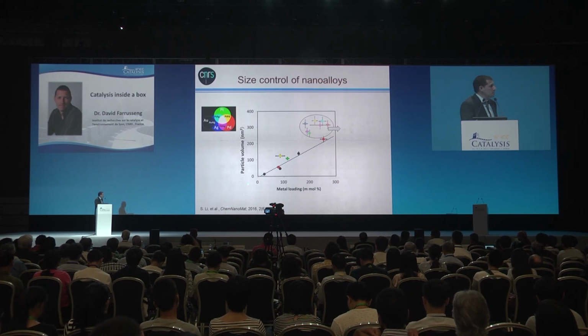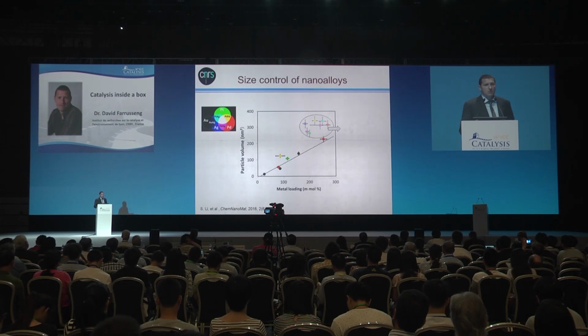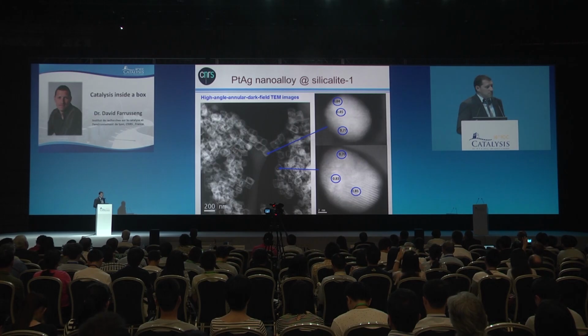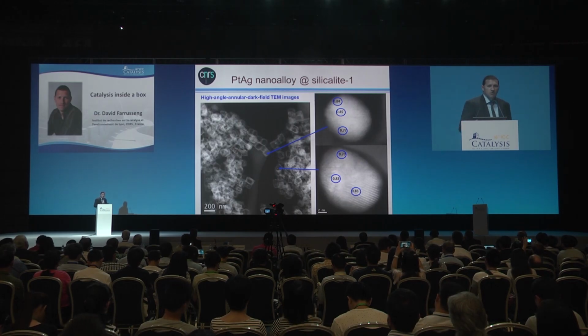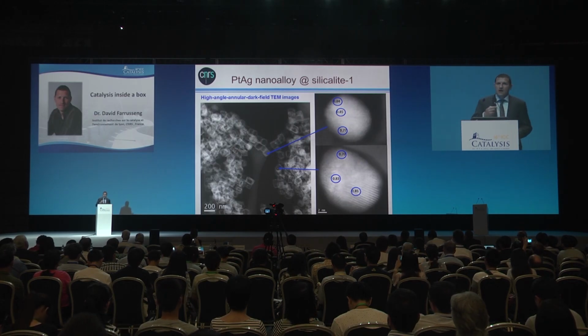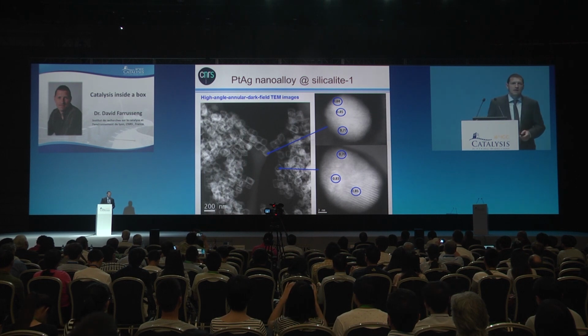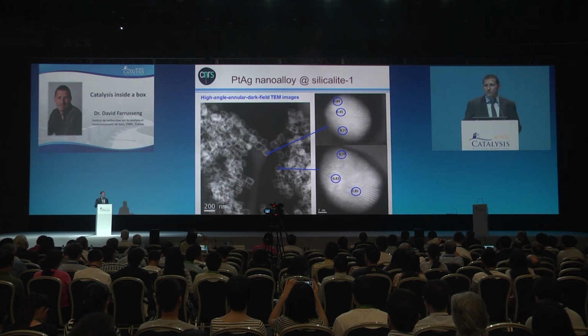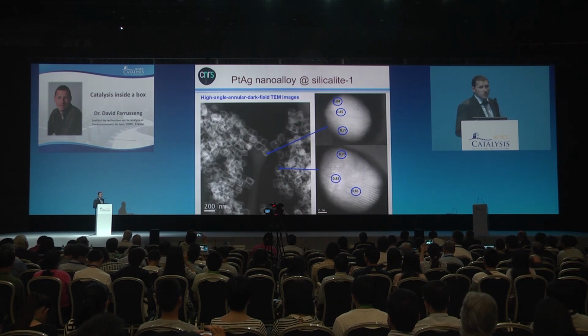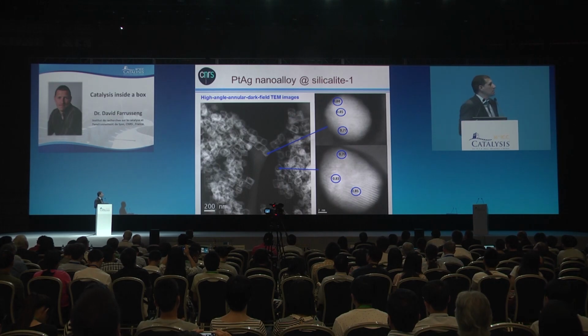ICP analysis, meaning that for all the highly loaded samples the metal content was underestimated. So we still believe it is following the linear relationship I showed you before. But our concern was not that. Our concern was whether we actually had alloys and the surface compositions of those alloys. So we have made deep investigations of the metal compositions in each particle by EDX.